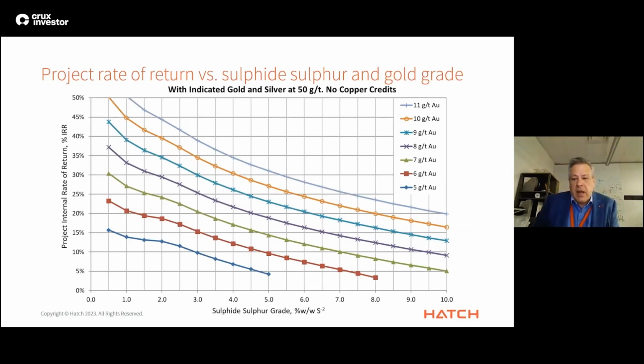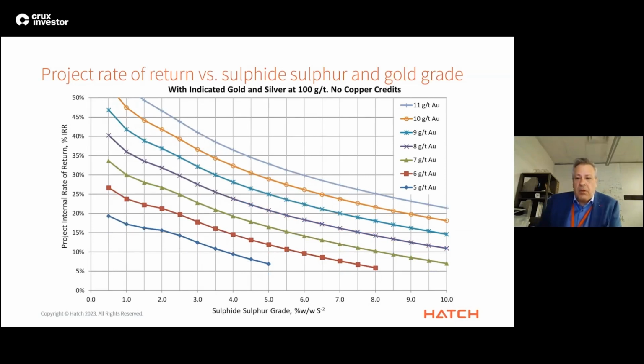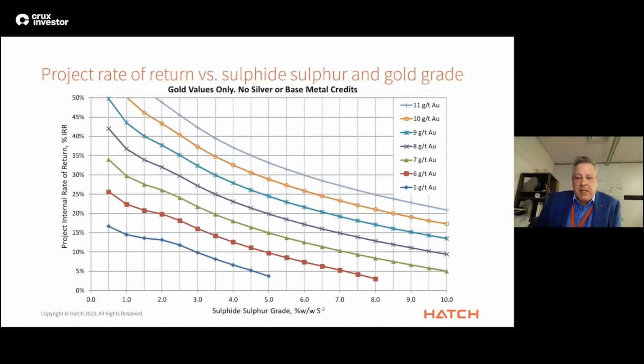ton. The IRR decreases as the added silver increases the carbon loading and stripping reagents, but does not offer the same revenue as gold. A further increase in silver grade to 100 grams per ton results in an improvement in IRR across all gold grades, as the additional loading of the silver influences the size and cost of the refinery, but it continues to add revenue. Now we return to the base case for reference just to see the impact of copper recovery on the project economics.